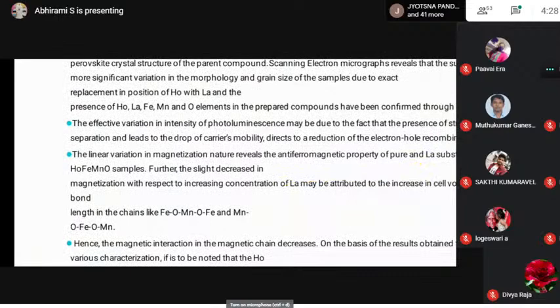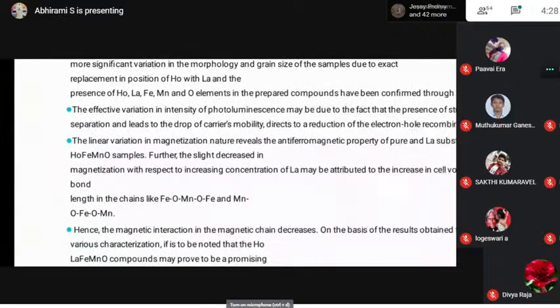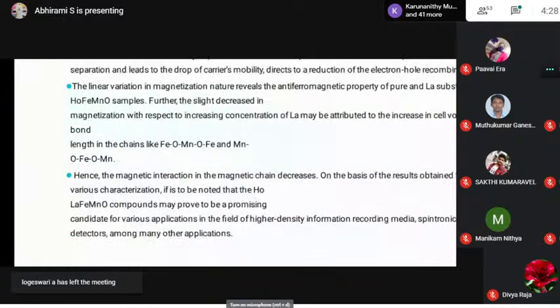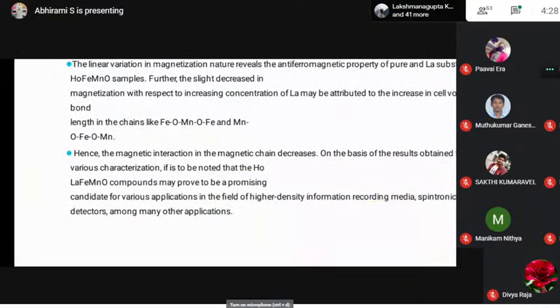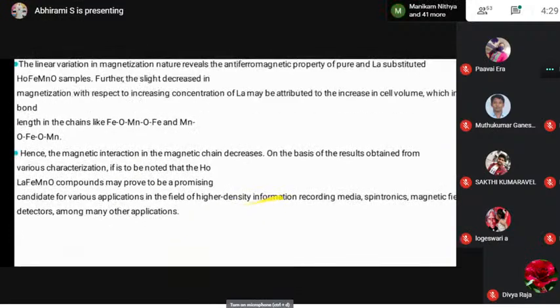Then the linear variation in the magnetization studies reveals the anti-ferromagnetic property of the pure and La substituted compounds. Further, there is a slight decrease in magnetization with the increase in concentration of La3+ ion. Hence, the magnetic interaction in the magnetic chain decreases, on the basis of the results obtained from the various characterizations. It is to be noted that the HoLaFeMnO compounds may prove to be promising candidates for various applications in the field of higher density information recording media, spintronics, magnetic field sensors, and infrared detectors, among many other applications.